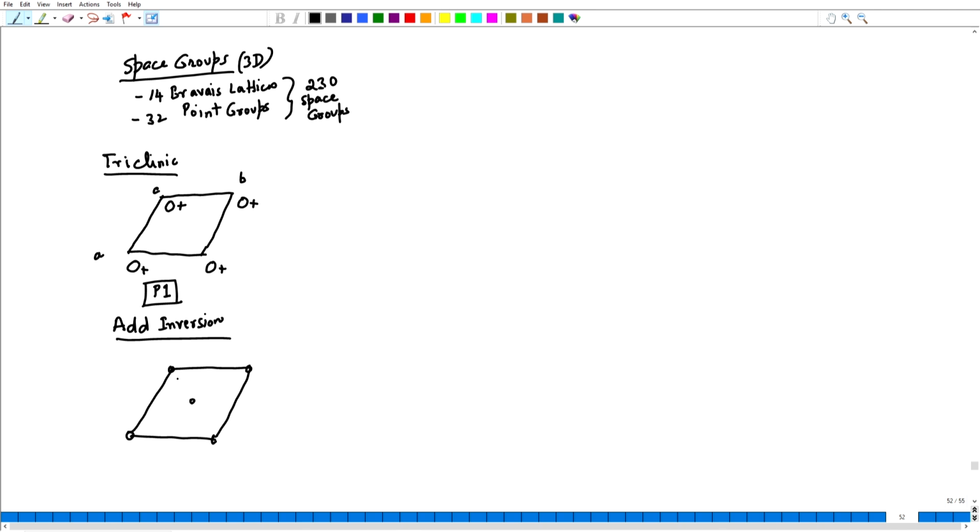Now, if I put an asymmetric motif above the AB plane, the inversion will take this below the plane and that I will designate as minus, and it will also change the handedness. So, I will put a small comma inside to indicate that I have now started from a right handed, it has gone to a left handed motif.